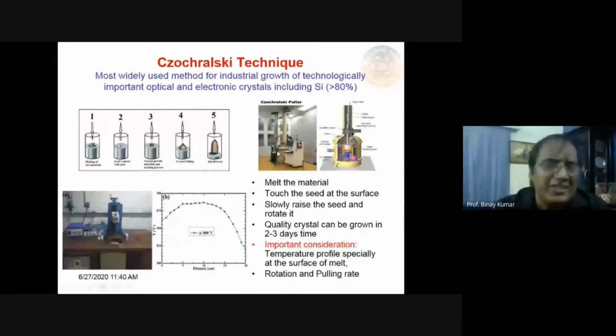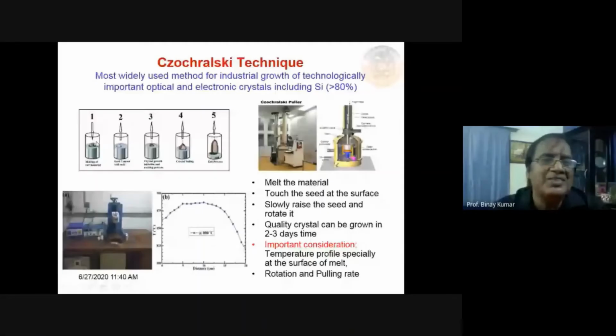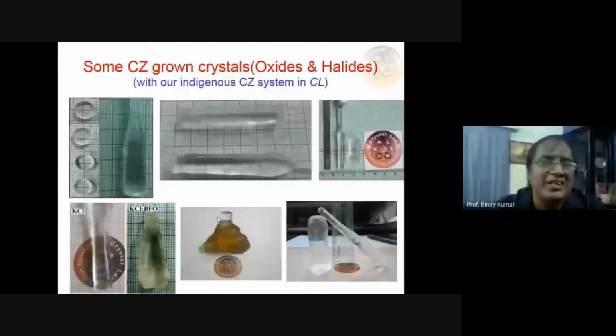So the basic principle is that we take the material in a crucible, then put a seed or a rod from the top, then rotate it and pull it, and the crystals will start sticking, and you get the whole crystal. This is our apparatus, and this is the temperature profile for halide, because it is about 850 or 890. So we have used this system to grow many crystals of oxide materials and halide materials. These are the crystals which we have grown.